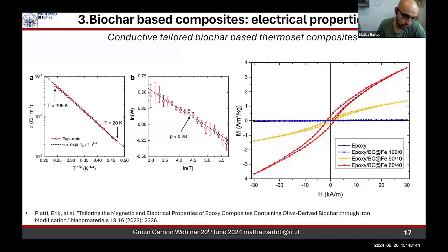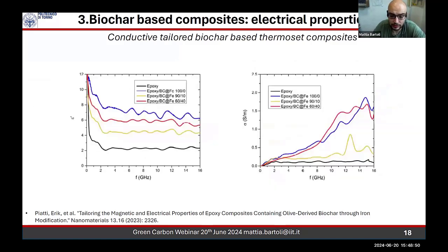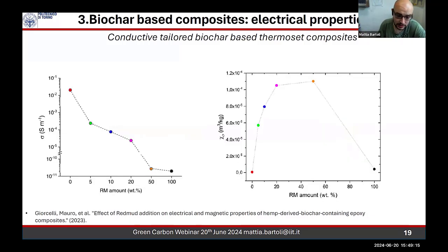But of course, we can also combine this approach with more sustainable ones. For example, this one is, just to conclude, the same trend that you saw before: increasing the percentage of biochar, you increase the conductivity. And if you increase the amount of tailoring agent, in this case iron, you do not decrease the conduction much. But if you replace iron with red mud and try to cut the impact of your material, you can obtain the same properties.